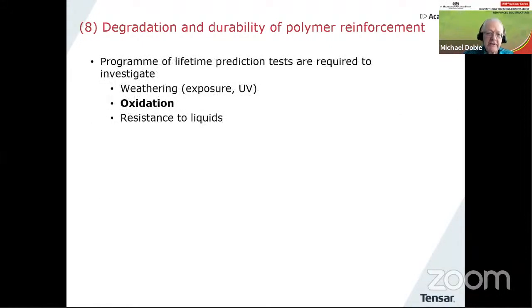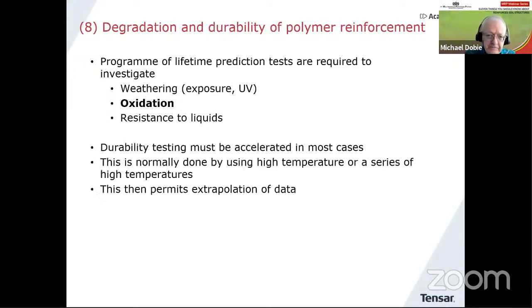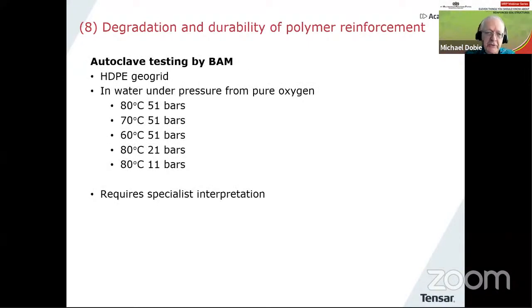Let's go briefly back to oxidation and talk about that for a couple of minutes. I'm going to show you one way of examining oxidation. Oxidation is one of the problems for the polyolefins like HDPE and polypropylene, and therefore we have to look at it very carefully. But in this case, we're going to look at testing using what's called an autoclave, which is some kind of cylinder where you put the material inside and you apply, in this case, high temperature and high pressure, and you take out specimens from time to time and test them to see what's happening to their strength.